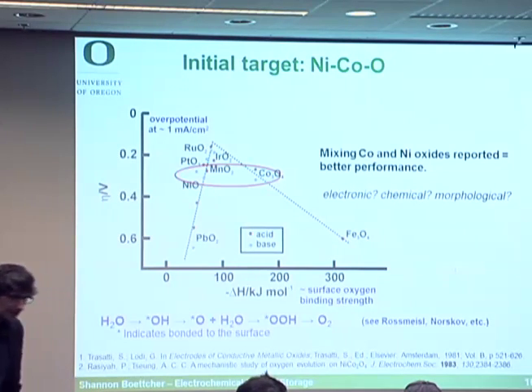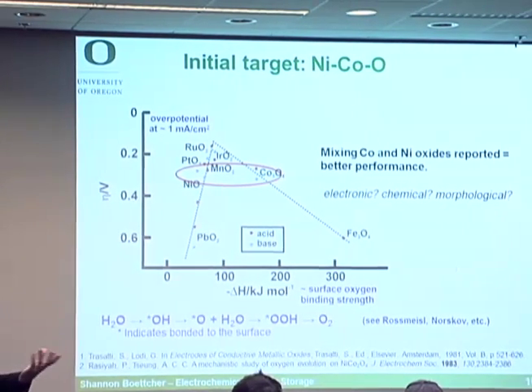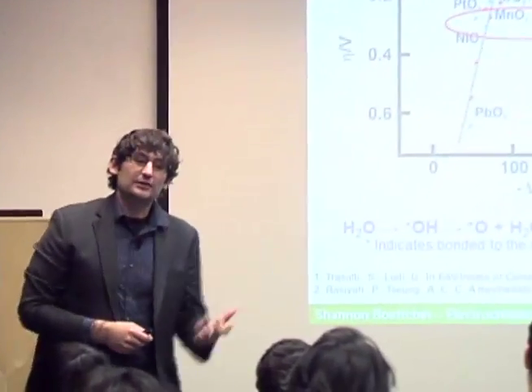And so when we started looking at systems to study, we first looked at what is known about the oxygen evolution reaction. And so this is what's called a volcano plot. This comes from the work of Sergio Trasatti. He's an Italian electrochemist, did a lot of beautiful work in this area. And the idea here is that you plot on the y-axis the activity of the catalyst. This is the overpotential relative to the thermodynamic potential for evolving oxygen in the electrochemical cell. And so if you have an overpotential at passing a given current density, a given rate of the chemical reaction, you want as small an overpotential as possible. That's high activity.